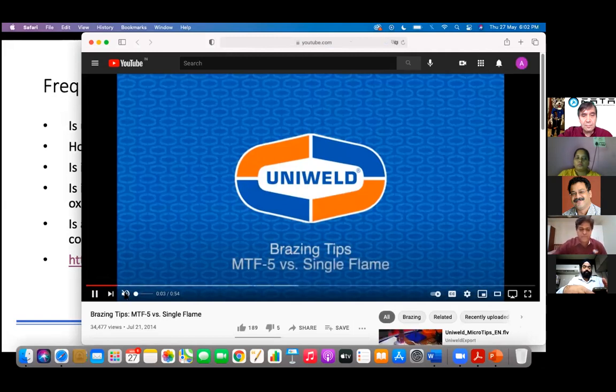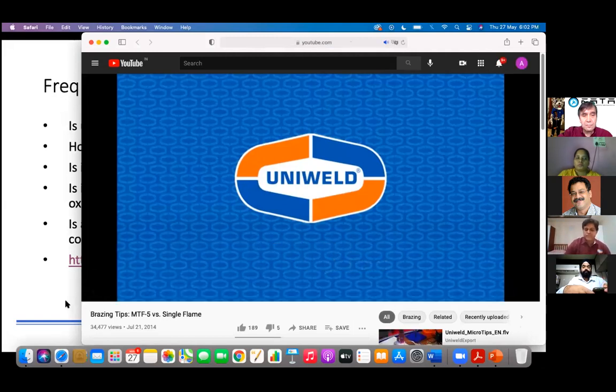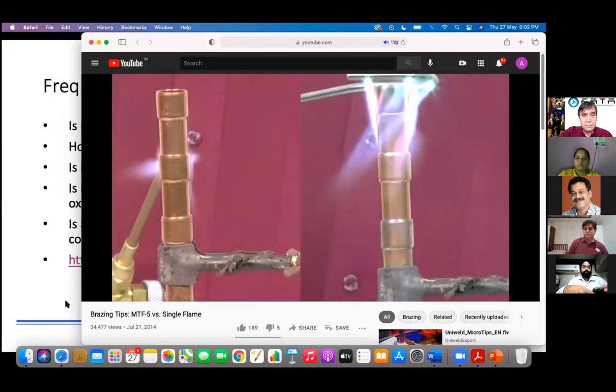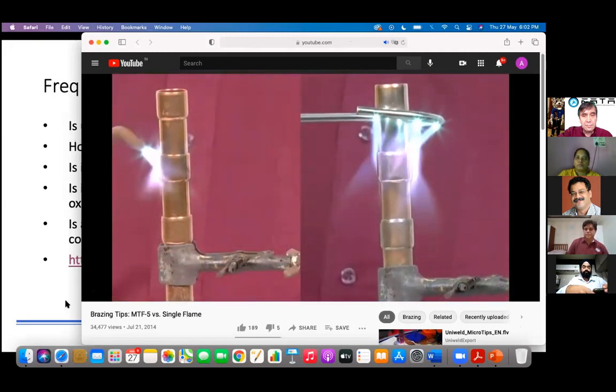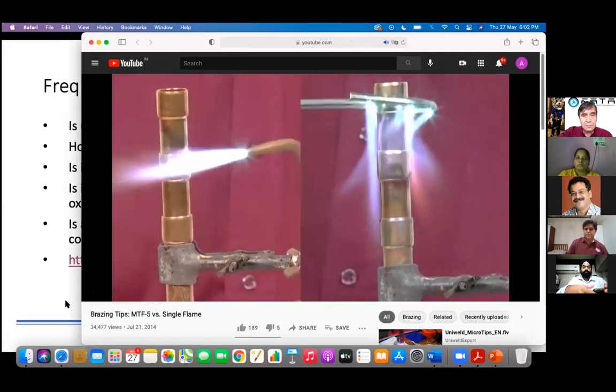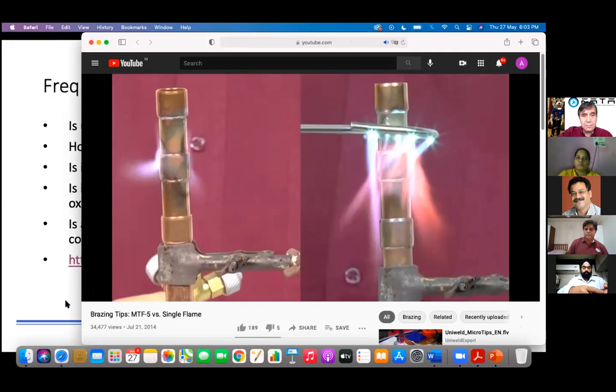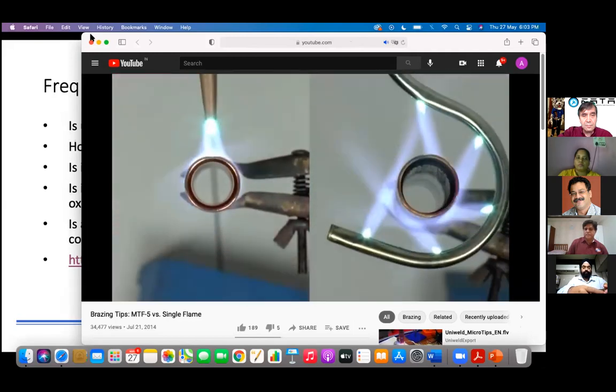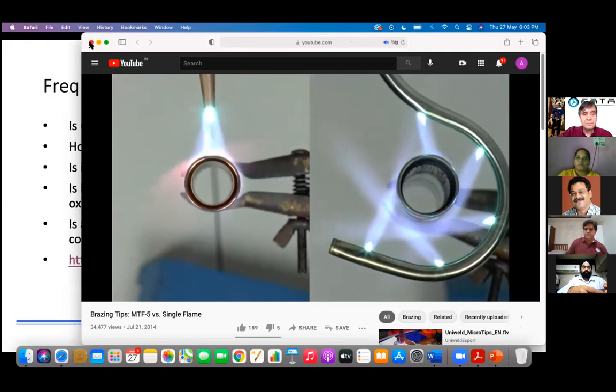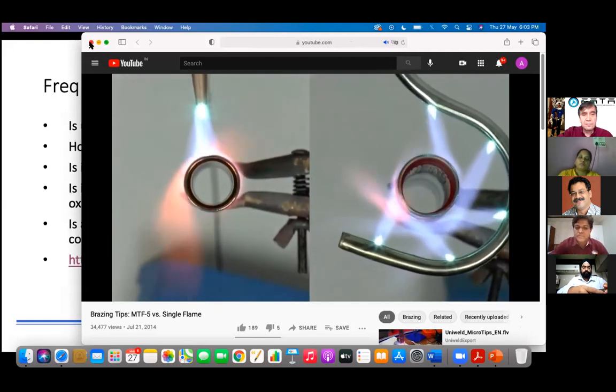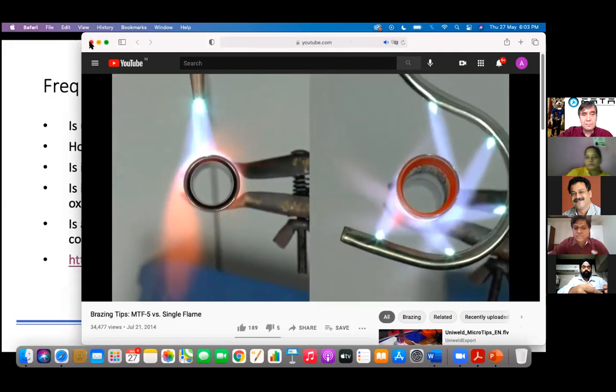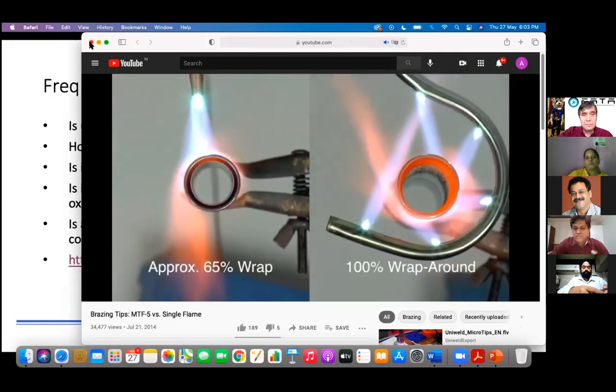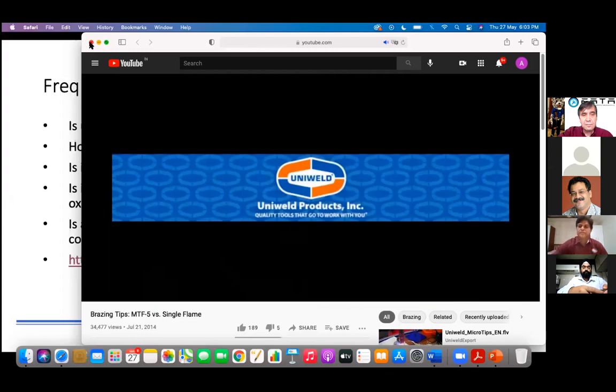Take a look at the performance of a single flame tip versus Uniweld's MTF5 multi-flame tip. With single flame tips, one must ensure to move the tip around the copper tube to achieve good heat distribution. With today's compact systems, this can be very difficult to achieve, particularly on the backside of the copper tube. Uniweld's MTF5 Captain Hook multi-flame tip, shown on the right, provides even heat distribution around the 360 degrees of the copper tube. In addition to providing 100% wraparound heat, the 40-degree flame angle easily flows onto the copper tube and away from sensitive areas, thus minimizing the chances of burning adjacent components. Uniweld, quality tools that go to work with you.